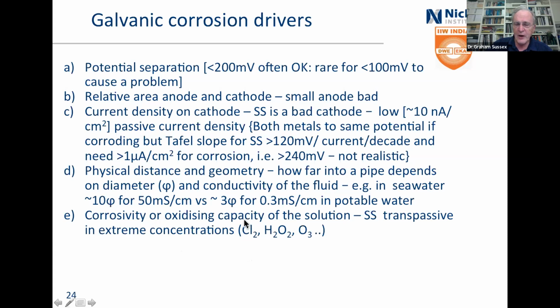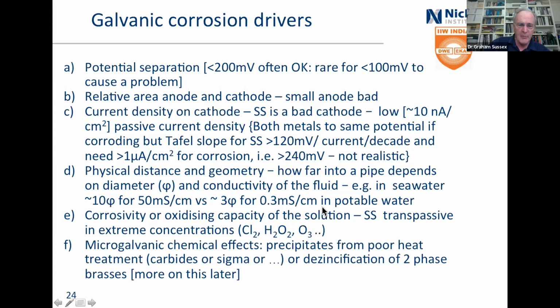If you've got really high levels of chlorine or peroxide or ozone and so on, then you can push your stainless steel right up into a transpassive region and it'll start corroding just by itself. But that's pretty rare, and it's nothing to do with galvanic corrosion. It's just simply corrosion. And microgalvanic effects. These are things like precipitates from poor heat treatment. So this is carbides or sigma or so on, from welding usually or heat treatment, or dezincification of the two-phase brasses. And I'll talk about that in a few minutes.